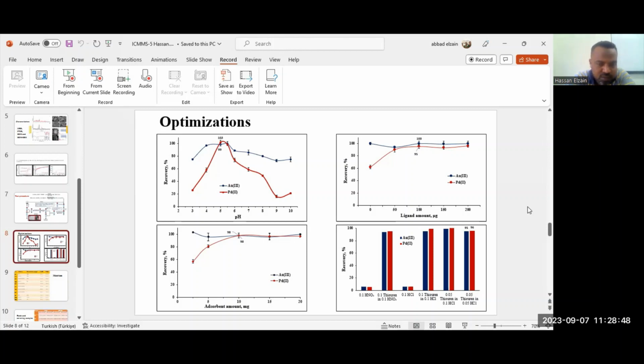pH. We use pH from 3 to 10. We tested this pH with buffer solution. We have selected pH 5 with buffer solution as the optimal pH. For adsorbent amount, we tested from 2.5 milligram to 20 milligram. We have quantitative results from 10 to 20 milligram. We have selected 10 milligrams as the optimal adsorbent amount. For ligand amount, we also tested from 20 to 200 microgram of ligand. Our ligand is PADAP. We have selected 100 microgram as the optimal.